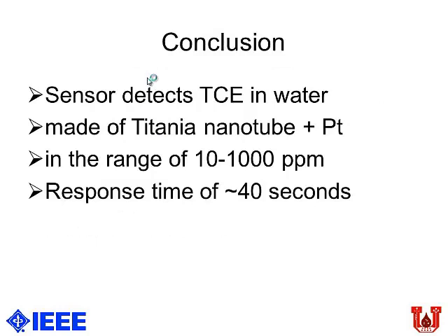So in conclusion, the sensor detects trichloroethylene water. It's a very simple system. You don't need any clean room technologies. It can go down to 10 ppm in water-based systems, and the range is about 10 to 1000 ppm. And it's a very fast response time. It's about 40 seconds.